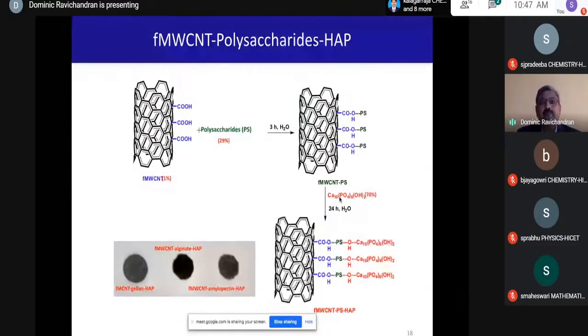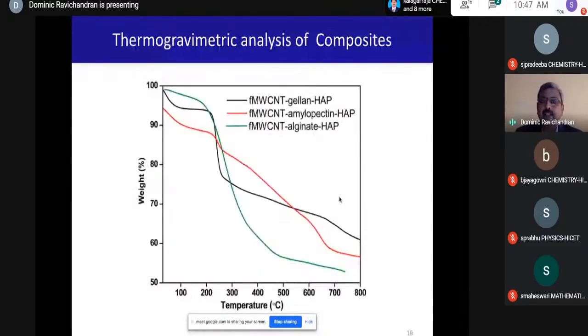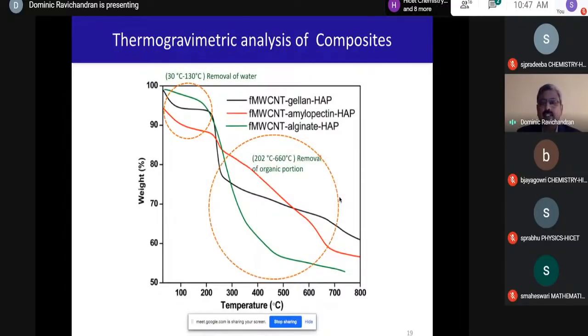We also perform thermogravimetric analysis of composites to see the thermal stability of the material. And we see that from 30 to 130 degrees, there is some water loss, and from 202 to 660 degrees centigrade, there is removal of the organic portion, beyond which it is very stable.